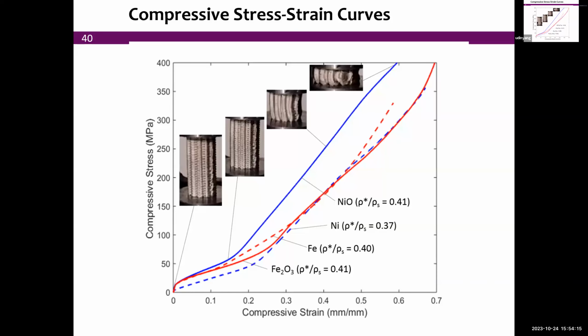And we do some compressive testing to demonstrate that those are fully metallic, they're ductile, so here's a stress strain curve. We see relatively low yield stress. That's because we have pure metals here that are not very strong. A strain hardening, if you want, which corresponds to the more or less uniform plastic deformation of those micro-lattices, and then a densification region where now multiple layers are starting to touch with each other. That is well beyond, of course, the range you'd be using it, but the area under the curve here represents the energy that is being absorbed.